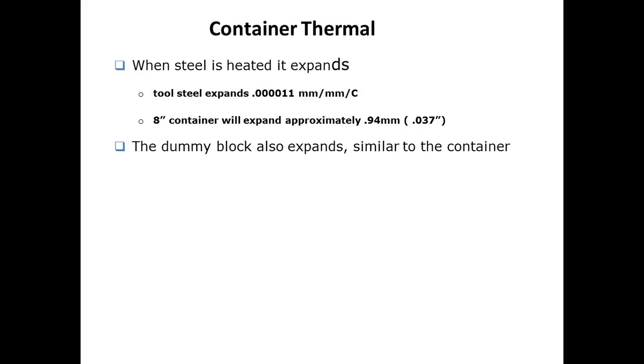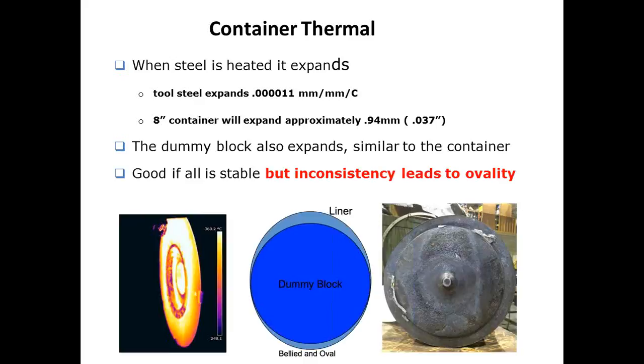The good news is the dummy block should be about the same temperature as the liner. And as long as the dummy block is the same temperature as the liner, the thermal stability or temperatures don't have much effect. Where this becomes a problem is we have many containers that can be 50 to 100 degrees hotter on the top than the bottom, in which case we no longer have a round and cylindrical liner, we have ovality. In these cases, you'll see blow-by or extruding by on the top and possibly the bottom of the dummy block.